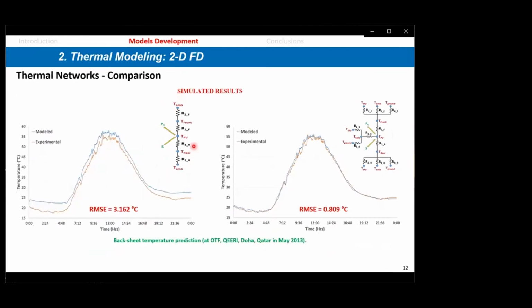As you can see, if we use the classical model for heat dissipation, we get some results that are fairly close to the experiments. The experiments are given here in red or orange, and the model is in blue, but with a root mean square of about 3. So not too close, but close enough. Now when we introduce our modifications of the heat dissipation, you can see the predictions are very, very close to the experiments with a root mean square of 0.8 only. So this is a very important improvement of the prediction of the temperature distribution or temperature in the PV panel.